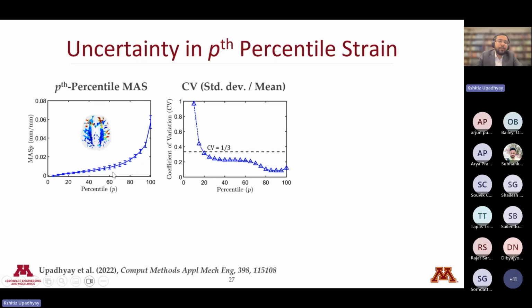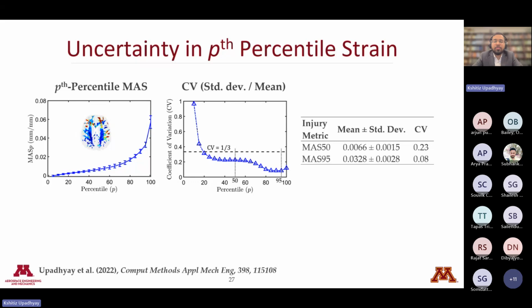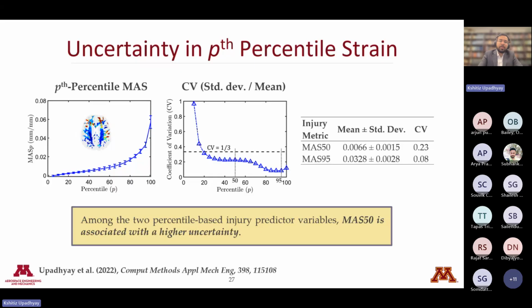So for example, here, 50th percentile strain is the value of the strain that is greater than 50% of all the data points on the brain tissue. And this was important to us because 50th and 95th percentile strain is used as an injury metric in the literature. So we use these 50th percentile and 95th percentile strain values as a predictor of the susceptibility of the brain to injury. And so this research told us that among the two injury predictor variables, the 50th percentile is actually associated with a higher uncertainty. So it was useful information.